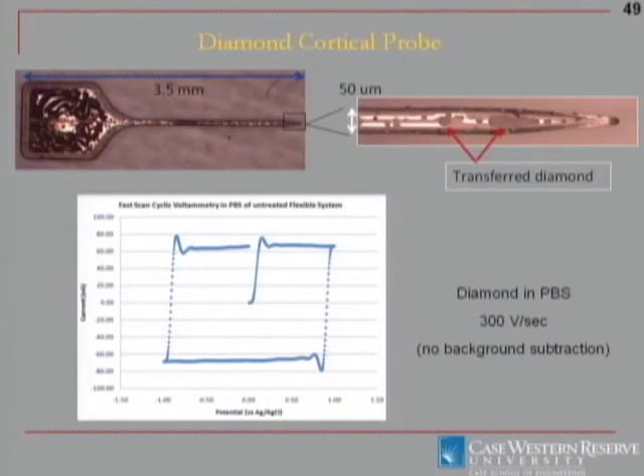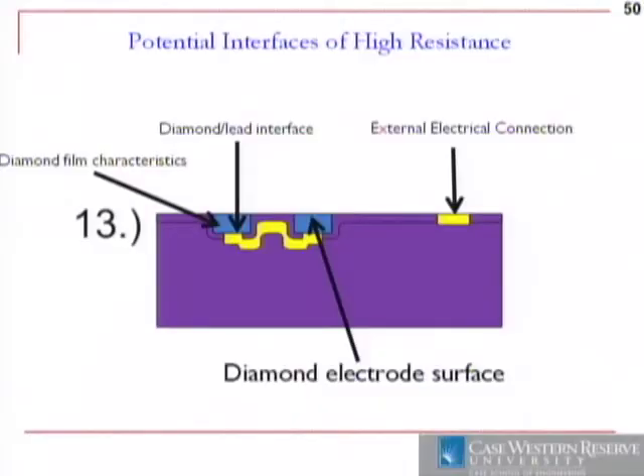What we had to work out is the fact that the diamond surface we've exposed has some kind of insulating layer on it. This is shown by the fact that we don't really see any electrochemistry, we just see a capacitive response. This is from a cortical probe. And there are various parts of this device where you could have a problem. I already showed you we have ohmic contacts at the connection, so we don't think it's there. But what we wanted to look at is the surface.